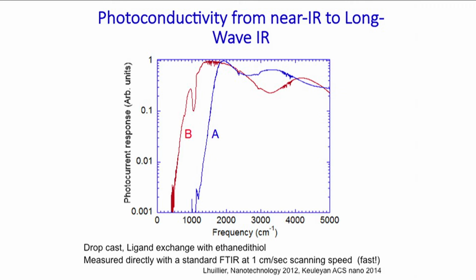And we've made some progress, and now this is an example of two detectors, if you will, made with different size of particle. This one detects the mid-infrared between 3 and 5 microns quite well, and this one goes all the way to 12 microns, or even further if we extend that log scale. Signal to noise is really good, and you can even see all the absorption from water in the atmosphere, from the CH stretch, from CO2 in the atmosphere, the CH stretch that's remaining from the ligands, and the water in the atmosphere. So all of this you can see coming out. And this is from the silicon dioxide on the substrate. So they work. They're fast. They're just not very sensitive in that particle implementation.